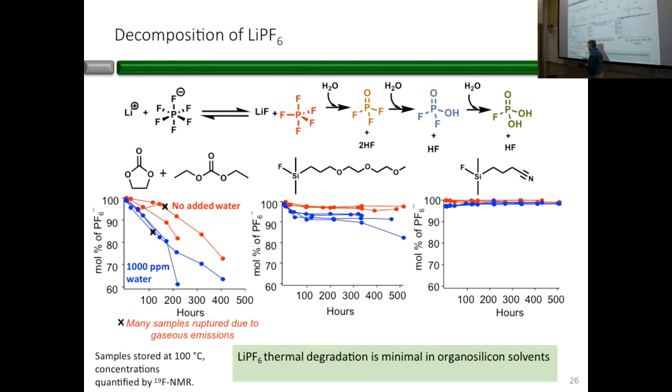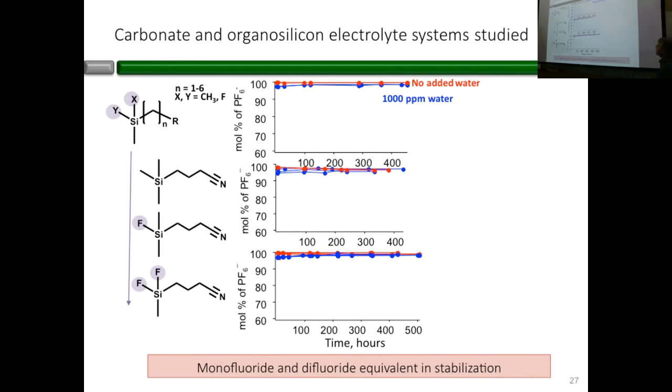Because one of the problems with lithium-ion batteries is that if they get hot, I don't know if you've ever taken your cell phone and left it sitting in the sun, but if you're in Arizona and you've got a car that's going to be sitting out somewhere in the sunlight, it could very easily get up to 100 degrees centigrade. This compound, I'm sorry, the dimethyl version of that boils slightly above room temperature. It's flammable even at room temperature. So the idea that you can make these stable up at 100 degrees centigrade really makes all the difference in the world.